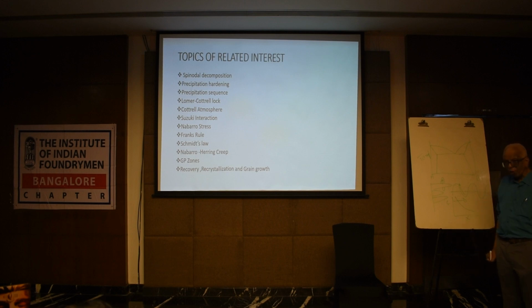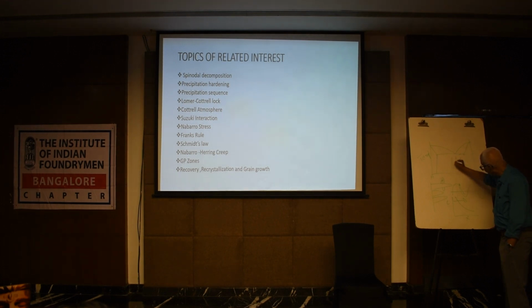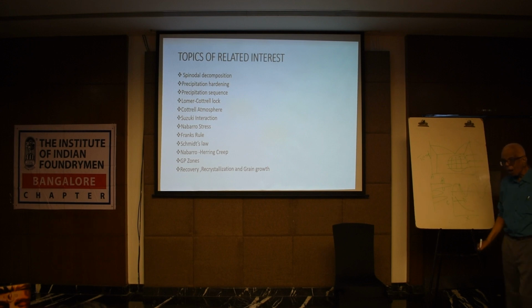Metastable precipitates are also very important because the most important thing in strengthening alloys is coherency. What happens is, for example, if you have atoms like this, this is a GP zone, the matrix is this, like aluminum, there's a strain in the lattice. There's a one-to-one matching of the matrix crystallographic planes with the GP zone crystallographic planes. So there is a coherency, a coherency strain field.